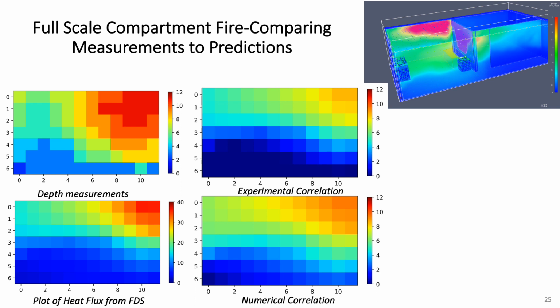We then compared that to the experimental correlation and the numerical correlation, and they all show a reasonable agreement in the general trend or pattern that the depth measurements from the actual experiment show, which is a plot of heat flux from FDS to both the experimental correlation and the numerical correlation. So what we did is we looked at the heat flux from the FDS, used that as an input for our own numerical correlations, then calculated the depth. So the deviations we are seeing could be because of the experimental and numerical study we used to develop the correlations, and the errors with the FDS. So the deviations are a combined effect of all this.